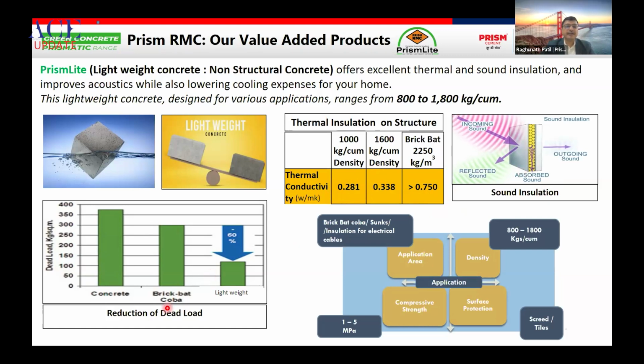And if you compare the load, for normal concrete, if the depth of concrete is 150 mm with 2500 kg density, the dead load comes to 375 kg per square meter area. Instead of that, if you use this lightweight concrete, the load comes to only 120 kg per square meter. Since the concrete strength is just 1 to 5 MPa, this is not used for structural application. This is used only for non-structural application.